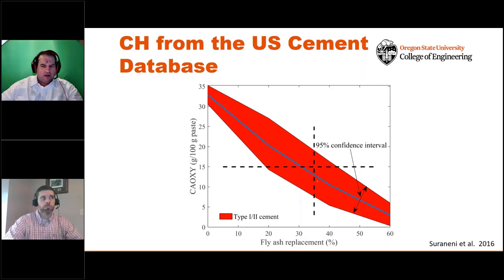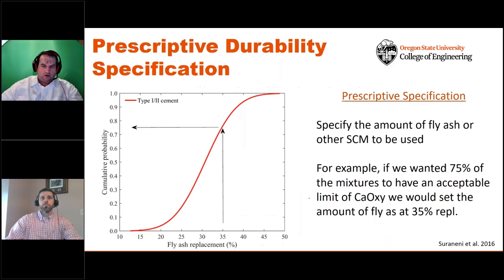And then when we started to add the fly ash into the system, we really started to see a huge trend that's consistent with what we saw before, the oxychloride decreasing as we increase the amount of fly ash. But what we can see is that band is relatively well distributed and is a really good normal distribution. So we can start to use this type of approach to describe the parameters that we should start to put on specifications if we don't know the composition of the fly ash or the cement that are going into this system. So all of a sudden now we can say, what is the level of probability of failure that we're willing to live with?